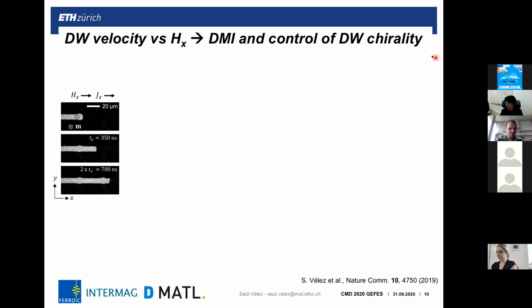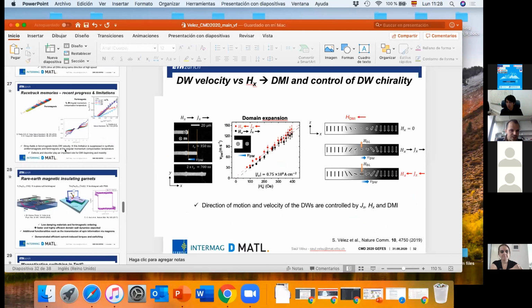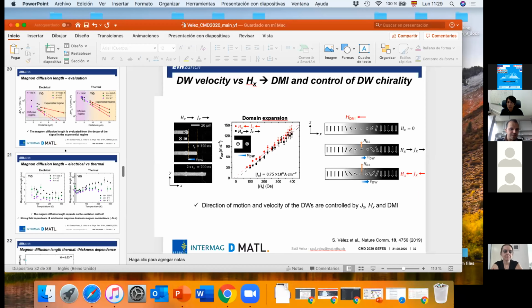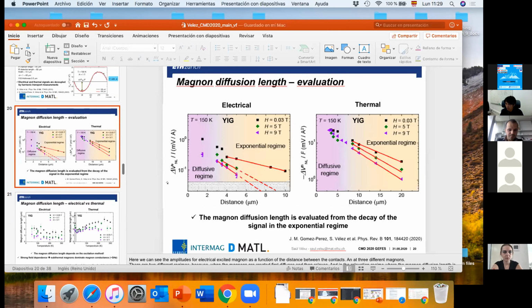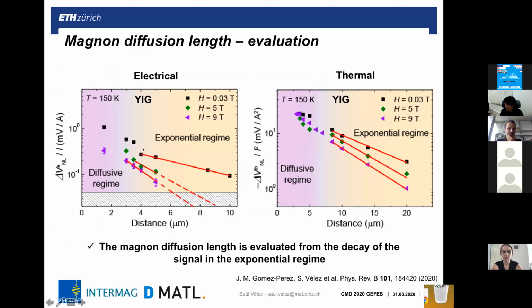So we measure the signal for different devices. We measure the decay as a function of the distance between the injector and detector, and by measuring the decay, we see that in the short range regime we have a diffusion regime, and we measure in the region in which we have a single exponential decay, and from this we can then determine the magnon diffusion length.